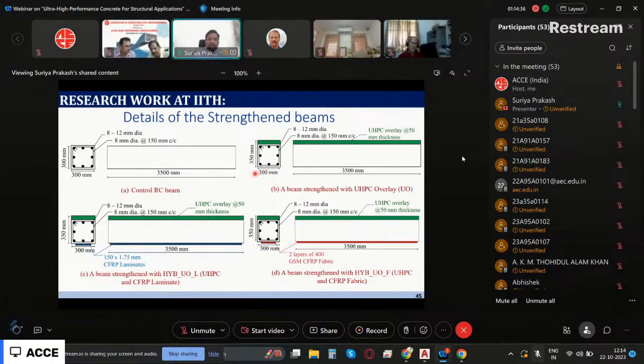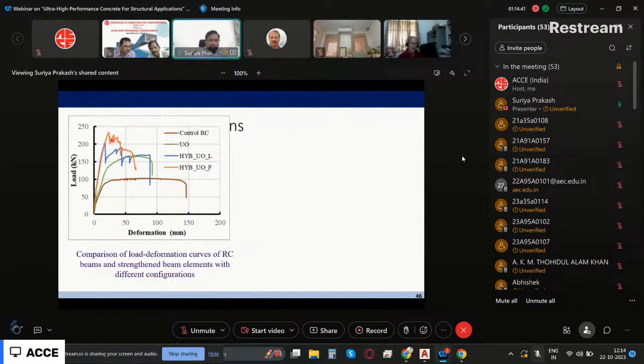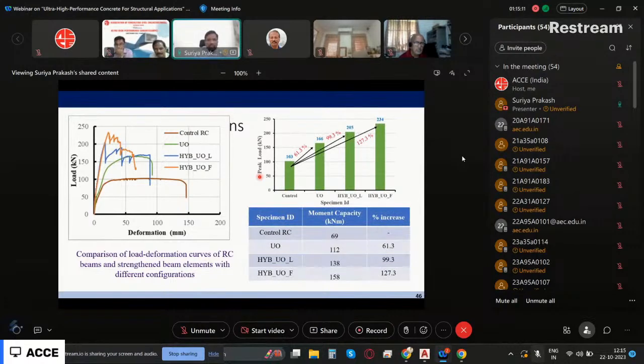You can use it. And we found that this UHPC overlay, for example, these are the different techniques, load versus deformation curve. And you can see that with the hybrid system with the fabric and overlay, the strength became 100 to almost 220 kilonewton. That means for an existing girder, if I can apply this UHPC overlay plus this FRP strengthening, I can double the capacity. I mean, because you have to do the calculations, and the stiffness also can be improved. So it's a very good strengthening technique also for existing systems. So that is what we have said.